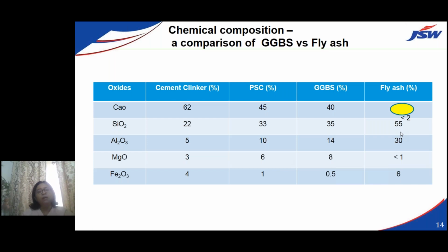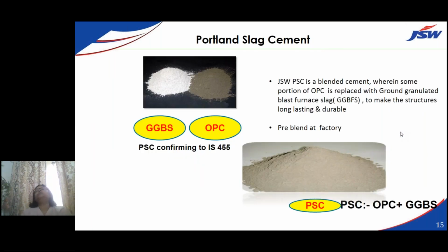So now the slag which is coming, this is coming from a controlled source, and the manufacturing is also controlled. Hence the slag which is coming is a product of controlled production. The parameters which we'll have will be as good as cement, or cementitious product, if not equally better. That's the reason if you see the IS codes are permitting replacement of slag up to 70%.